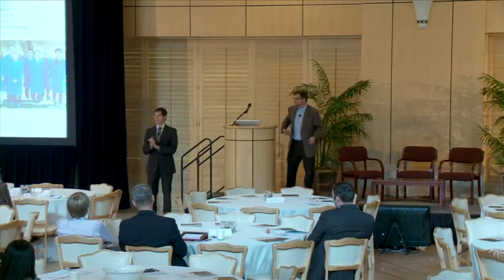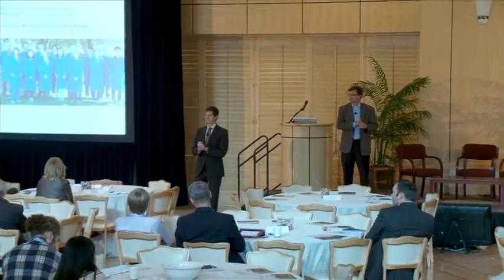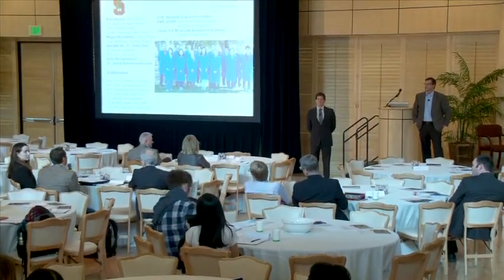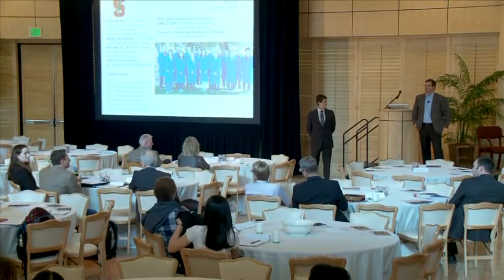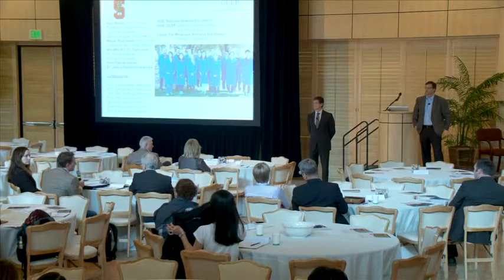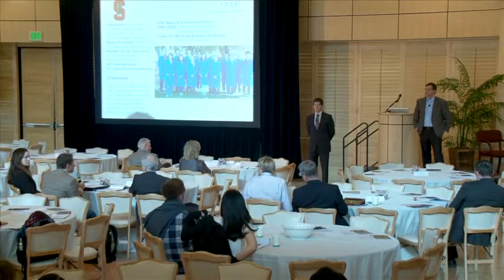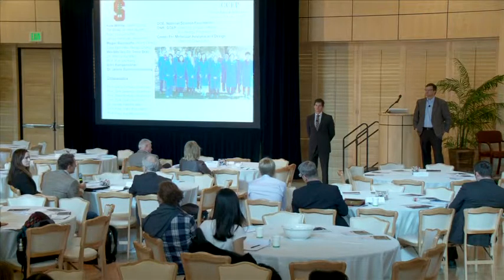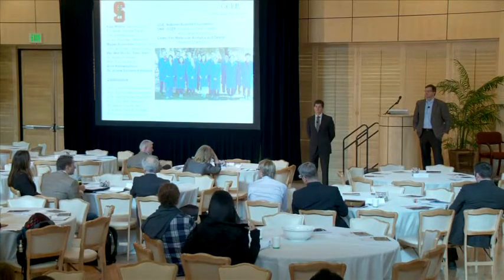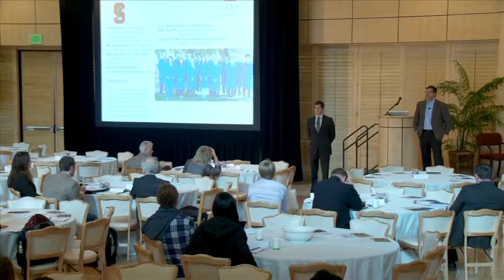Thank you, Bob. Questions? Yes. Rob Brown, Colorado School of Mines. Just one comment, I guess. You spent some time emphasizing how to activate CO2. Of course, we could raise its temperature. That would be one way, and electrochemically reduce it in a high temperature solid oxide system that makes use of more perovskite material systems. And I can electrochemically reduce it at very low overpotential quite effectively. And I can do it simultaneously with steam and make myself a nice syngas, which I can then use downstream for fuel synthesis. So just another possible pathway that was shown in the other presentation.